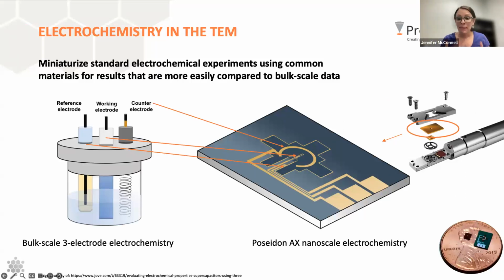And so what we've done is our best to miniaturize the standard three electrode cell that you would use to do electrochemistry on the benchtop. We've got the three electrodes here. The working electrode sits right on top of that viewing area in that window, which is what you saw in pretty much all of the examples here. You could see a portion of that working electrode, which is where a lot of the dendritic growth was occurring. You've got a large counter electrode here. And then you've got a reference electrode patterned right back here, a little bit out of the way from the working and the counter, so that if any bubbles are generated during the experiment, they don't interfere with the reference electrode and the job that it's doing.